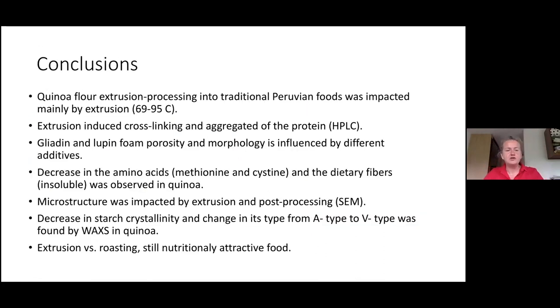So to conclude, for instance, quinoa has been processed by extrusion using temperatures between 69 and 95. Surprisingly, these were fairly good temperatures to play around with and still not damage, for instance, nutritional aspects, and still get the product well processed. Although we can't avoid using temperatures, and can't avoid protein cross-linking and aggregation. So we have to live with it.